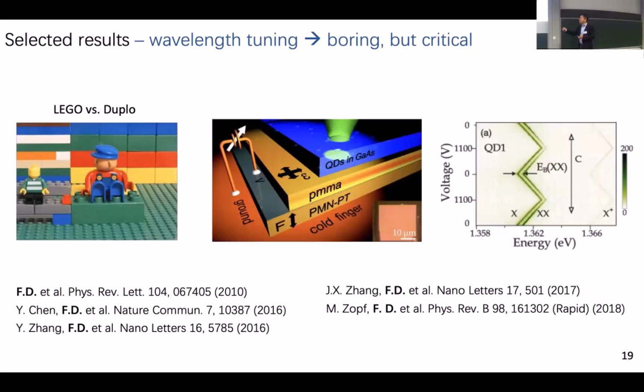This is something we had to work with some years ago, because in order to generate some meaningful strain from the piezo, you have to achieve a certain amount of electric field. And this piezo is pretty thick, a few hundred microns thick. So you have to supply this voltage. So it was a dangerous time. We improved that afterwards. I'll show you later.